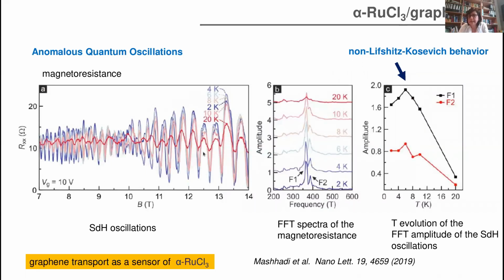So what they observe here is shown as a function of magnetic field. If you do the fast Fourier transform, this basically gives you the hole pockets that you build into closed hole pockets within the graphene. And the temperature evolution of these amplitudes does not follow a Lifshitz-Kosevich behavior.